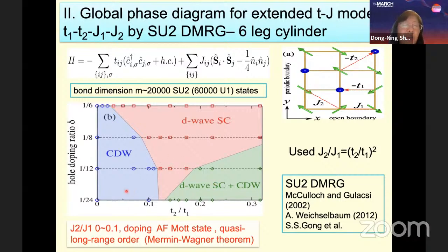For the small T2 region, indeed what we get is CDW dominant. When we increase T2 over T1 to be slightly larger than 0.1, we go into the D-wave superconducting phase with very uniform charge density.